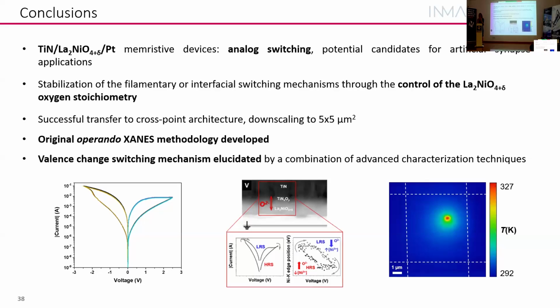So Joule heating will heat for sure the region where it's occurring, and then the oxygen mobility will be higher in that region because it's hotter. So probably there will be more oxygen drift in the region close to your filament where there's Joule heating. Here it was also a way of visualizing where the filament is because it heated. So we used it as an indirect way of seeing where the filament is, but of course it will affect your switching for sure, that region will heat. And if we really believe that it's oxygen vacancies or ions, that is the same. There will be more in the region that is hotter.